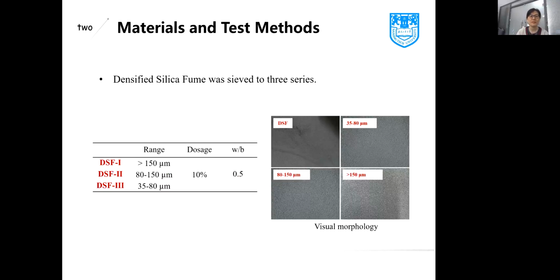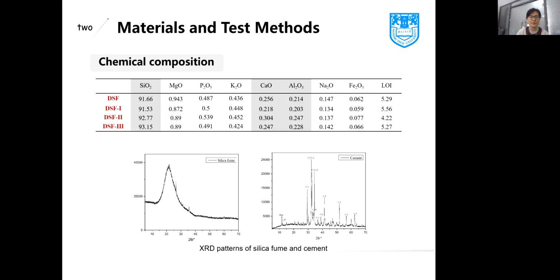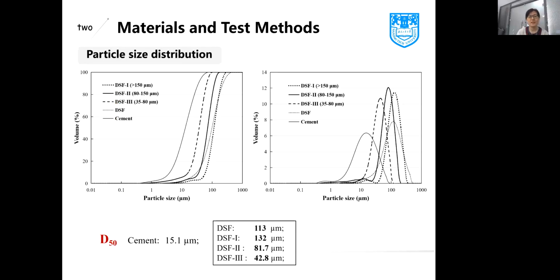The densified silica fume used in this study was sieved into 3 series. The dosage is 10%. Water to binder ratio was 0.5. This is the visual morphology of different types of densified silica fume. We studied the chemical compositions. You can see the change of the fineness of silica fume has no obvious influence on the chemical composition, but it influences the particle size distribution.